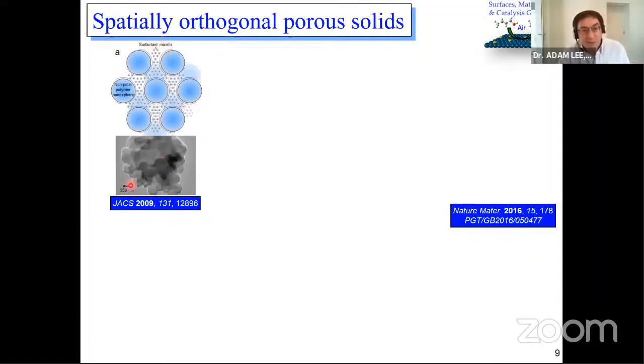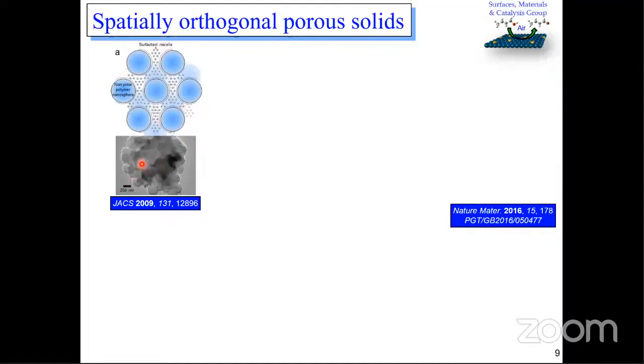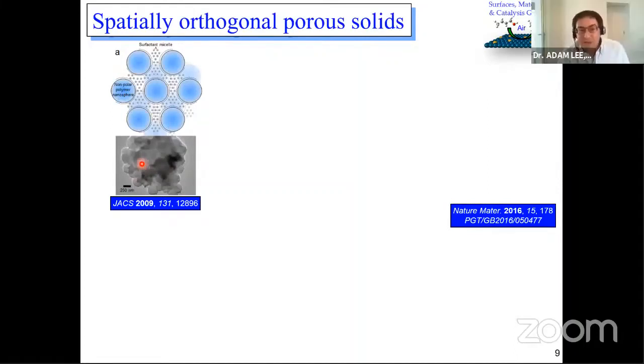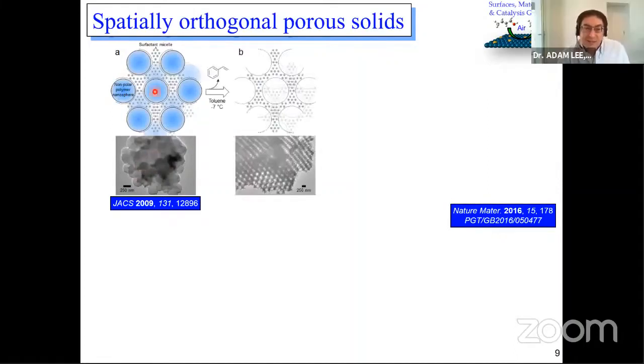Now, this by itself looks horrible. If you look at the TEM, you would go, how would he ever publish that? He wouldn't. So the trick here is to not leave the templates in. The trick is to take the templates out one at a time. So we've managed to selectively detemplate the macropores using a cold toluene extraction. So we can now empty the macropores whilst the mesopores remain blocked.